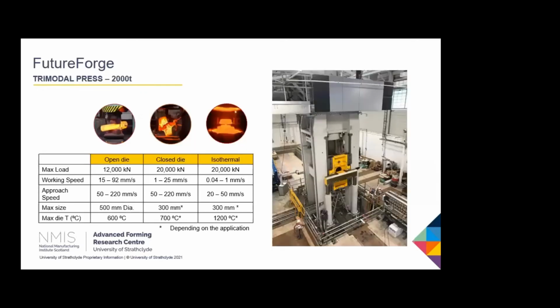Okay, so what does the machine do? What are its capabilities? Here it's a trimodal press, with a maximum load of 2,000 tons. For the open die, it's 1,200 tons. The closed die and isothermal, it's 2,000 tons capability. In the open die mode, it's a reasonably fast, slowish machine really in some respects: 15 to 92 millimetres a second stroke rate. The closed die is around 1 to 25 millimetres a second. And for isothermal, we've got control between 0.04 and 1 millimetres a second.